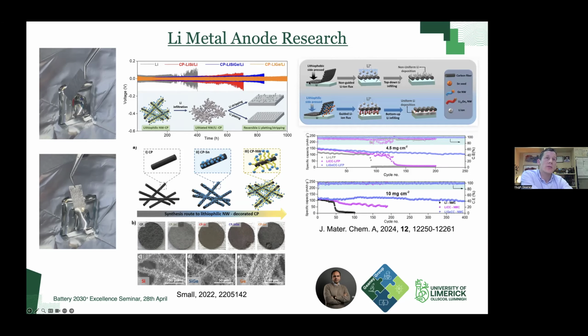And we had two scenarios here. One where you just use that carbon cloth directly on the lithium metal anode, and another one where you coated it with lithophilic wires. Again, this was our germanium, and they were grown in low loadings intentionally onto that carbon cloth that you have here. They were then placed down on top of the anode. What you can see here, and I will show it based on SEM analysis on the next slide, is that this encourages bottom-up lithium infilling into that structure.